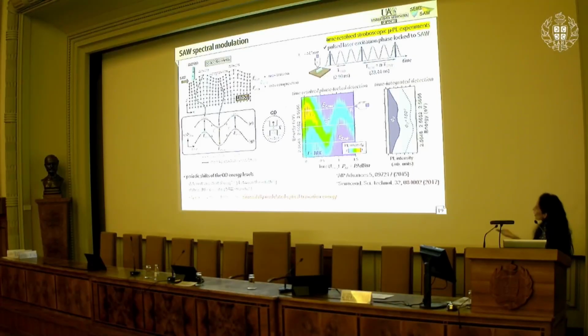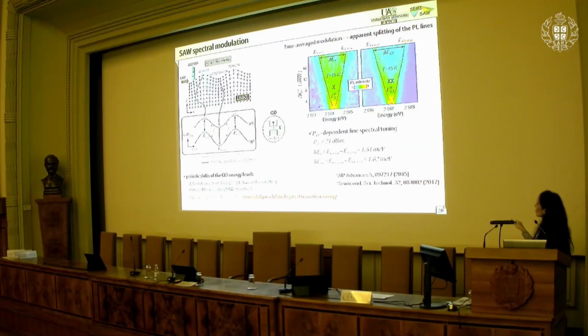In other words, as the acoustic wave propagates and couples to the nanowire, the embedded quantum dot is periodically strained, so its transition energy oscillates sinusoidally, as you can see here, changing from a minimum to a maximum value with respect to the equilibrium energy, this one here, in the absence of the acoustic wave. You can also see this, very evidently, in the time-resolved stroboscopic measurements, which are performed under pulsed optical excitation synchronized with the acoustic wave. So we can clearly see that during the decay of this transition, it has a sinusoidal modulation. Now, if we average this in time, we will again observe the splitting of these two lines, like on the previous transparency.